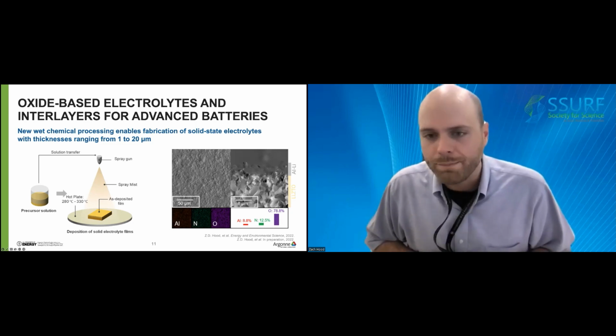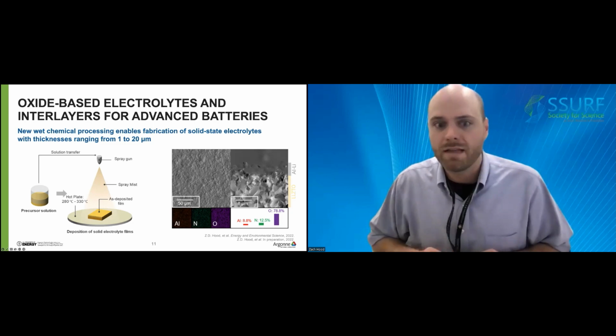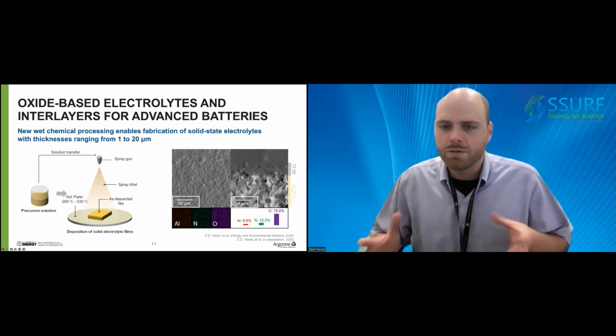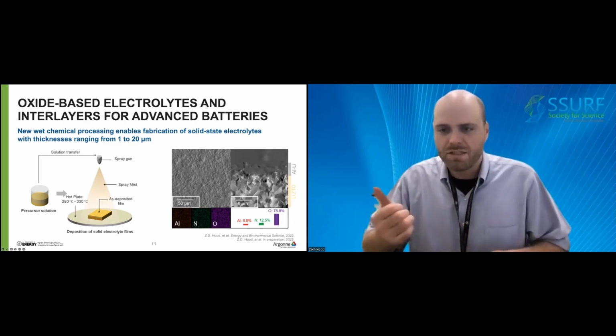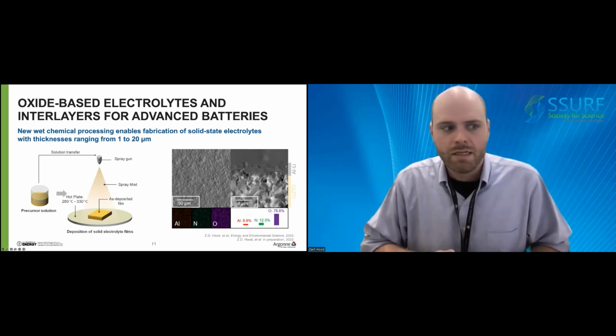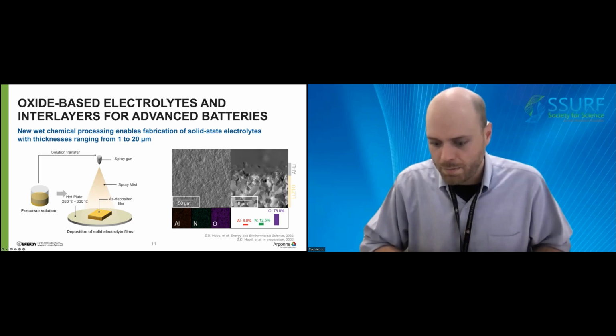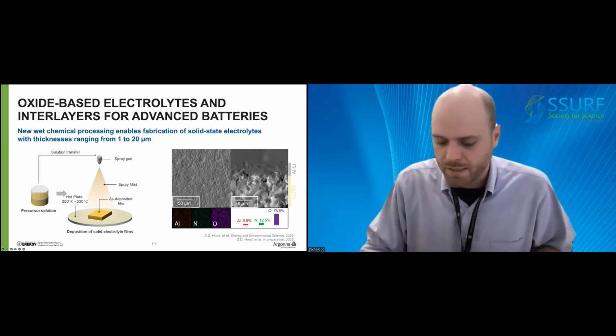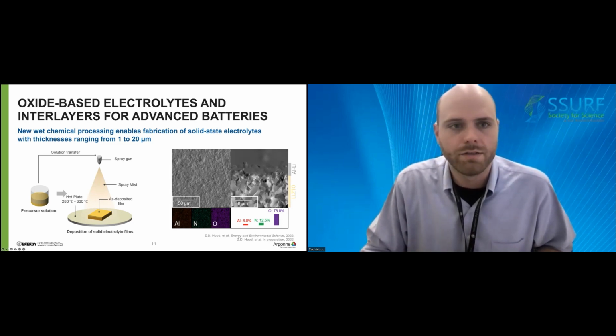But importantly, this method has allowed us to start to grow films that have thicknesses between 1 and 20 microns, high density and are pinhole free. And this is what we envision to enable the manufacturing of some of these next generation solid-state batteries.